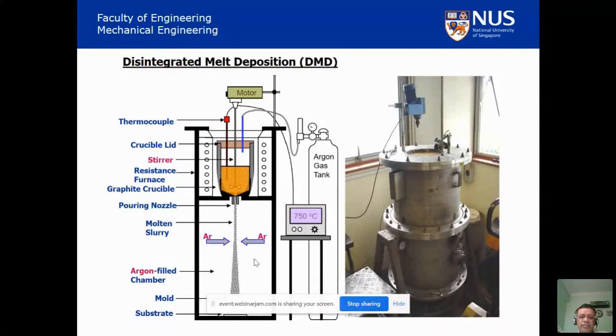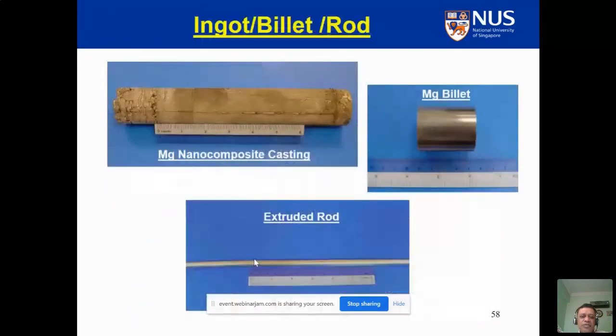We take the material in a crucible, we heat it, in the case of magnesium, to 750 degrees centigrade, and we homogenize the metal and the reinforcement. We bottom pour it so that we can get almost 100% yield. And when the material is being poured, it is hit by an argon gas jet so that it is disintegrated into small droplets and then deposited on the substrate. This is a kind of ingot we get.